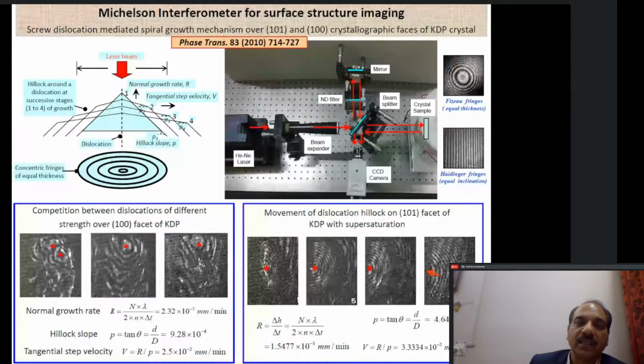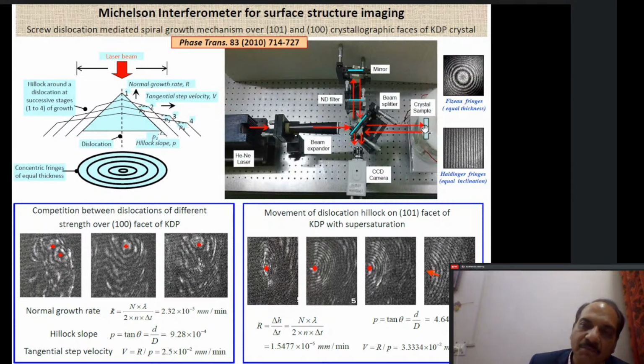What we do in this technique is you have a helium neon laser, you have a beam expander, you have a beam splitter, so half of the beam will go this way and half of the beam will get reflected. And this is the chamber where the crystal is growing. So in this chamber, you have the surface of the crystal which is growing, so we will make the beam get reflected from the surface of the growing crystal, and these two beams, the reference beam which is reflected from the mirror and the test beam which is reflected from the crystal surface, will come and interfere, and the CCD camera will record these interferograms.